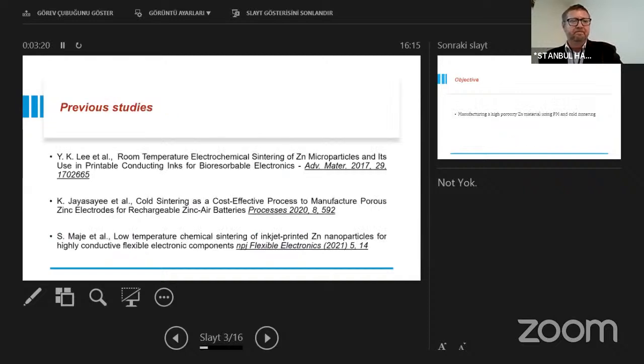Some breakthrough occurred some years ago when groups found a way to chemically sinter zinc nanoparticles, using a completely different approach. They sintered nanoparticles inside conductive inks. The idea is okay, but with the solutions they proposed, it is impossible to make 3D parts. Two-dimensional parts is okay, you can do everything you want, but to construct a usable three-dimensional part is a problem.